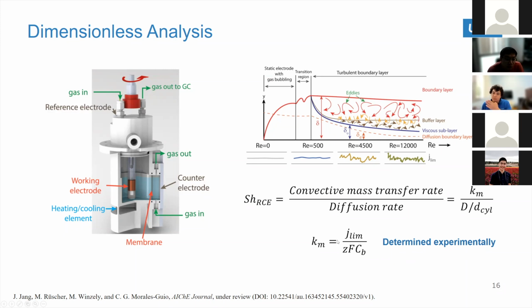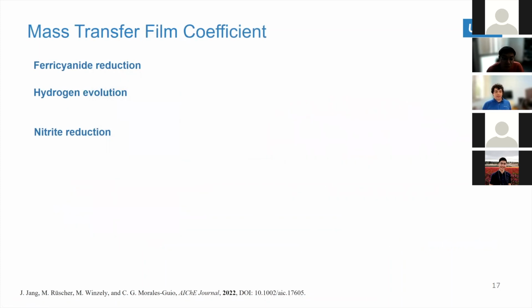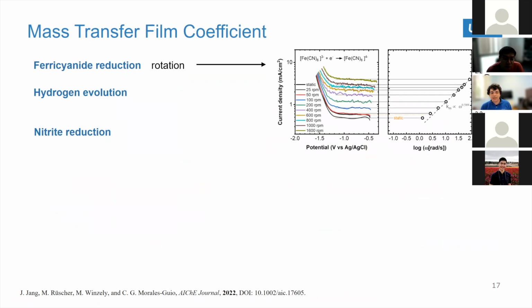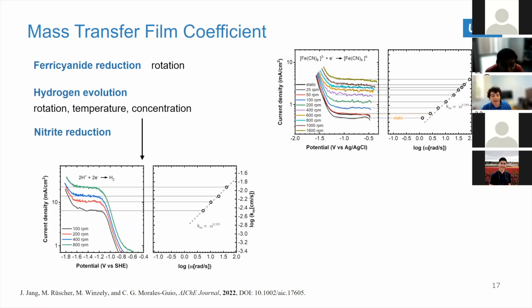So what we do is simply apply a potential until we see a plateau in the current, right? And if you know how many electrons you have in that process, then you can determine how many moles you're reacting per second per square centimeter. And because you know the concentration of the species in the bulk, you can extract this Km value, okay? What is important here is that we did different reactions. So we look at ferricyanide reduction. Again, as we change the rotation, we look at the plateau in the current. We're just limited by mass transport, and we can extract these Km values for different rotations, even though it's the same molecule. We can do hydrogen evolution as well.